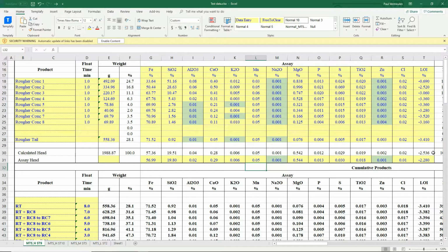The LOI is minus 2.5, so that tells us that it wasn't pure magnetite going in, and something added some positive LOI, which could be carbonates, CaCO3, MgCO3, or perhaps some goethite, or some other things with combined water or combined carbon units. Okay, so this is the data we have.